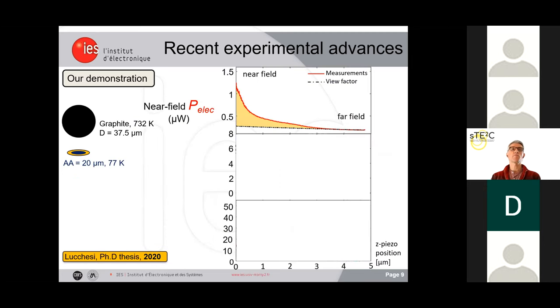This is the case of a graphite spherical emitter at a temperature of 732 Kelvin. And you see as a function of distance, the increase of the electrical power. And in this case, we find a near field enhancement of 4.6. But you have to remember that here we have a sphere-plane configuration for which the near field radiation exchange is much smaller than the plane-plane configuration.